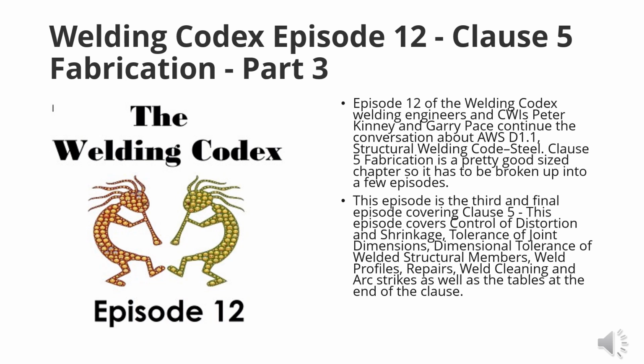Now we're going down. What do we got next there, Gary? Groove dimensions. We got non-tubular cross-section variations with the exclusion of electroslag and electrogas welding, and with the exception of 5.20, the root opening in excess of those allowed in the figure. The dimensions of the cross-section of the groove weld joints, which vary from those shown on the detailed drawings by more than these tolerances, shall be referred to the engineer for correction. For non-tubular cross-section variations, and this doesn't count electroslag, you go look at this chart, and it's going to tell you, all right, this is what's allowable in this Figure 5.3. We're going to cover the figures later on in this podcast. Yes, because they're all shoved in the back of each clause now. It's a little harder to handle both at the same time.